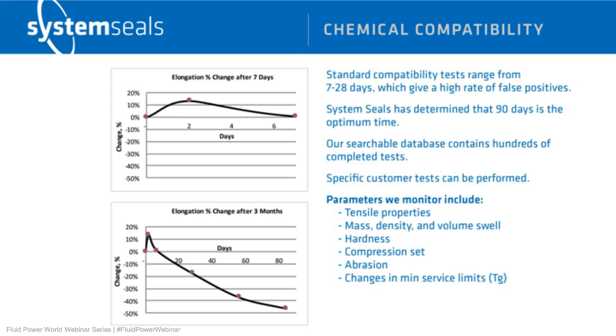So if we look at just one quick example of that, over 7 days, the change in this one particular tensile property increased by about 10%, and then it reduced back down to 0%. There was effectively no change. In a 7-day test, we would say this is compatible. But if we look at the results over 90 days, we see that even at the 1 month mark, 28 days, the property is only changed by negative 20%.